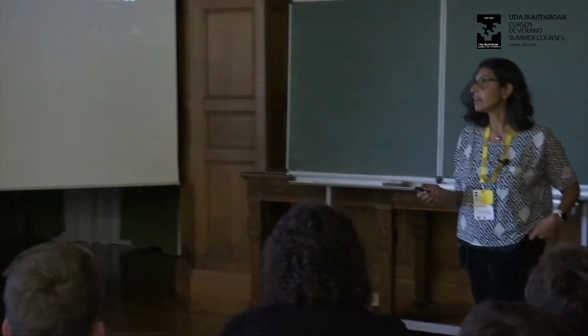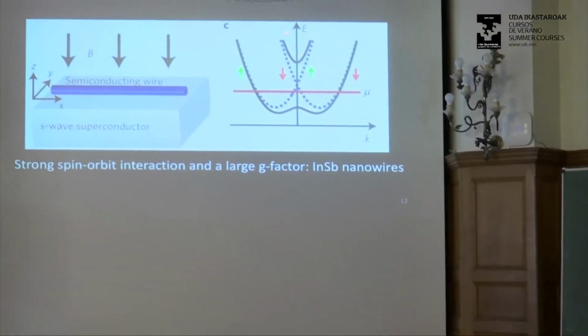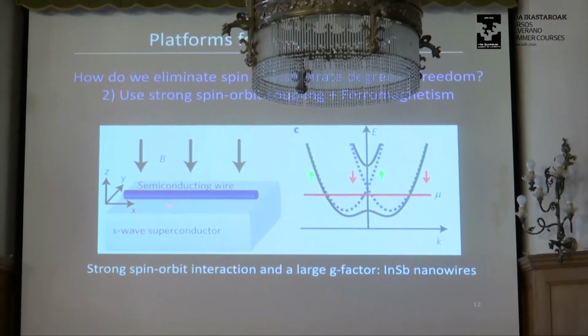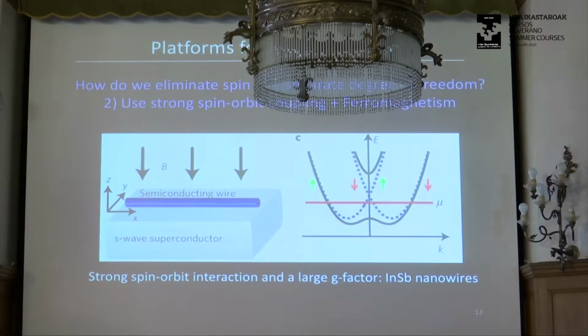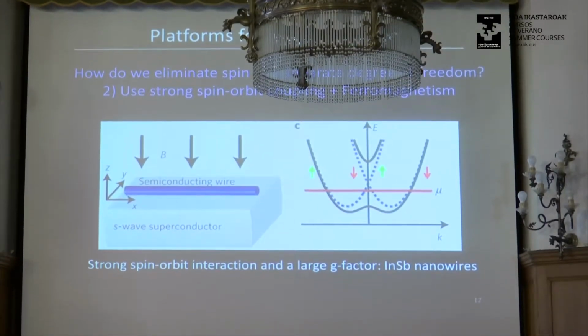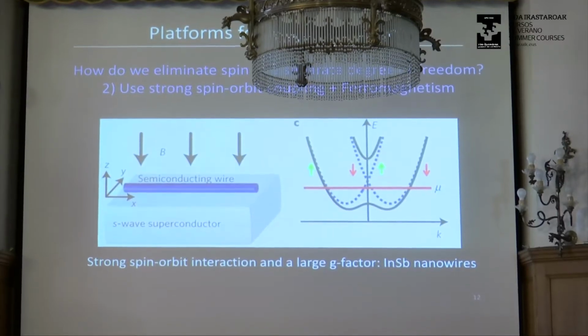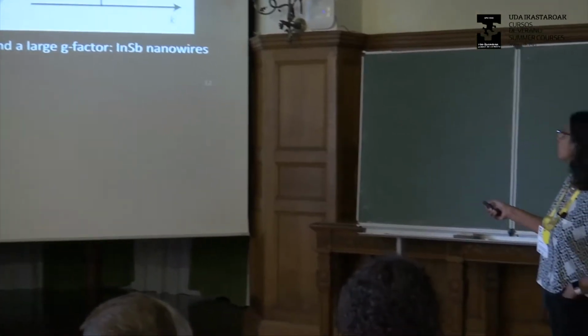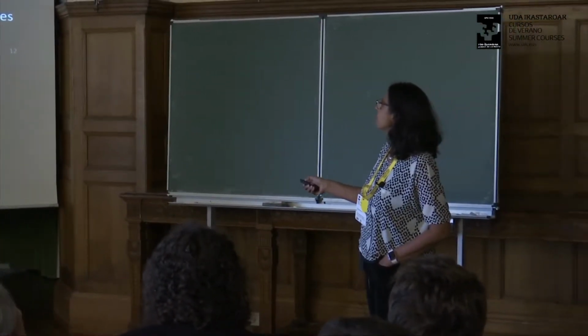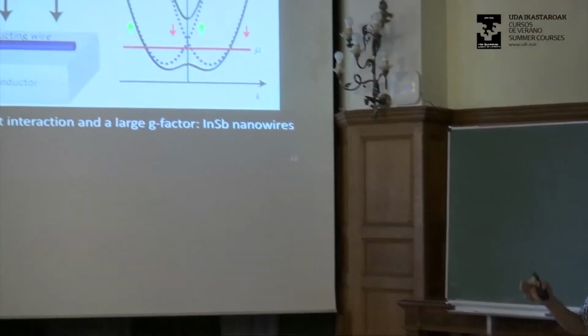Another possibility is, like Charlie said, you can use something with strong spin-orbit coupling. So let's consider this possibility. Let's take a semiconductor with strong spin-orbit coupling, right? And in this semiconductor, you would have these Rashba split states due to the strong spin-orbit coupling. That's these dotted lines. Now let's turn on either a magnetic field or couple this to a magnet somehow. If you do that, you can create a gap here, right? And then if you can tune the position of the Fermi energy such that the chemical potential lies inside this gap, you've achieved your objective. Basically, you've gotten rid of one of these branches, and you're left with simply one dispersing branch, right?